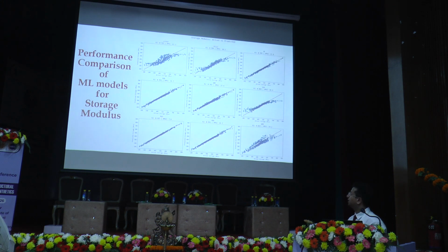I used 9 machine learning models to train this and to see how much error I am getting. You can see the predicted data on the y-axis, and on the x-axis the actual experimental data. If your data is coming on the 45-degree line, that is your best machine learning model. I used 9 machine learning models from all families, and there is an MLP model, multi-layer perceptron, which is an artificial neural network, a feed-forward model. This was giving a higher R-square value of 0.997. So this was the best model, and I chose MLP for storage modulus.